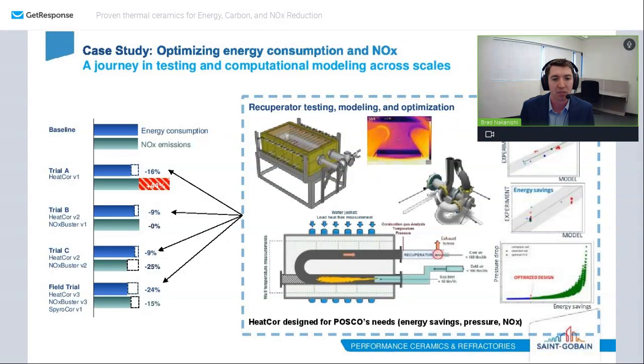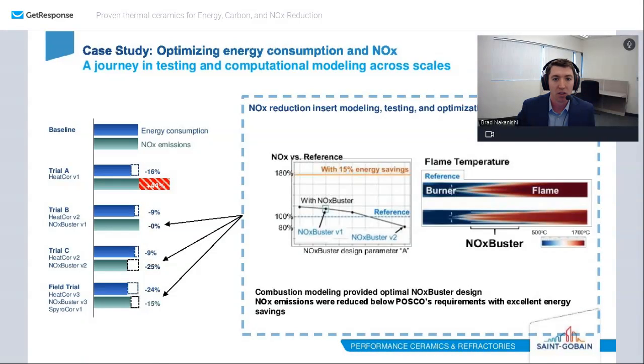Notice in trial A, that is using HeatCor version 1 without a NOx buster, provides 16% energy savings while increasing NOx by more than 40%. This is a direct result of the higher combustion air preheating while using the HeatCor. To combat higher NOx, the NOx buster, a ceramic insert positioned downstream from the burner in the flame, reduces peak temperatures and NOx, as you see in these figures on the right.